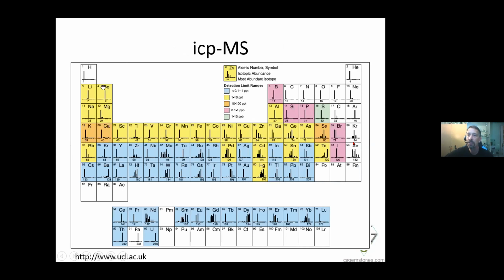However, what information can we get? You see here the periodic table of elements, and everything that's colored here can be measured by ICP-MS. It's just a couple of elements like hydrogen, carbon, nitrogen, oxygen, fluorine. Unfortunately, chlorine sometimes cannot be measured, but everything else can be measured very, very sensitively. So if we go down here to the rare earth elements, we have a detection limit of about one part per trillion. The other ones parts per billion. So you might know parts per million, but this is another step and another step, parts per trillion. So this is almost nothing that you need to remove from your gem in order to detect it.